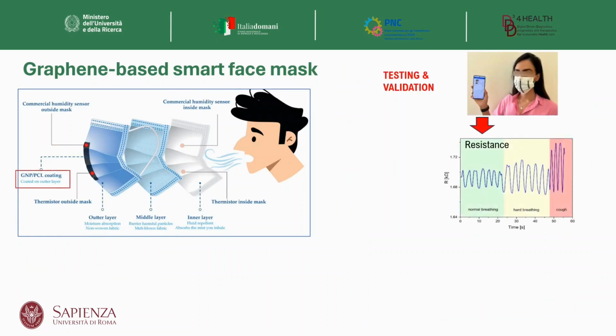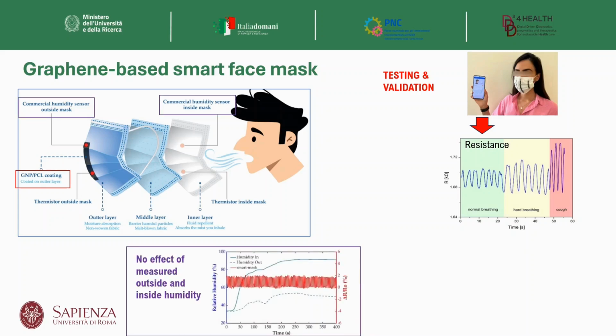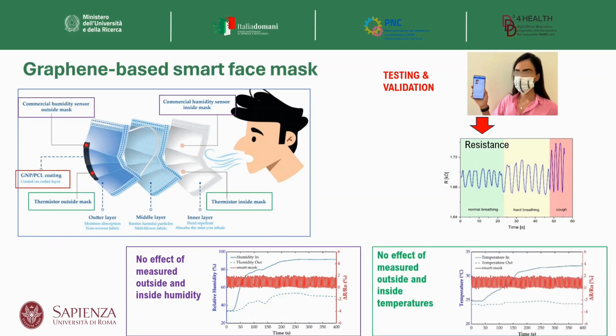Of course, we tested our sensor. The sensor that you see here is located outside the mask, just printed, and you see here the measured signal. We assess no effect on the measured data of the outside and inside humidity. So we place a humidity sensor outside and inside, so the measure is not sensitive to that, and no effect of the outside and inside temperature.